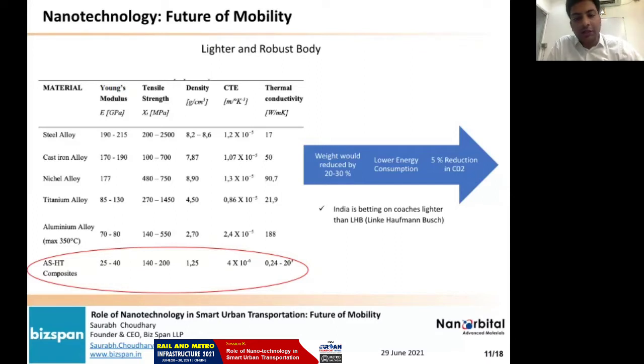So you can see that the ASHT composite has the best Young's modulus, excellent tensile strength, the density is the least, and the linear temperature coefficient is also at its best, and the thermal conductivity is also excellent for this ASHT composite. So it was proved that if this material is used for coach manufacturing in the railways, that can definitely reduce the weight by 20-30%, and it will also cause lower energy consumption. And the carbon dioxide reduction will be up to 5% if these coaches are used.